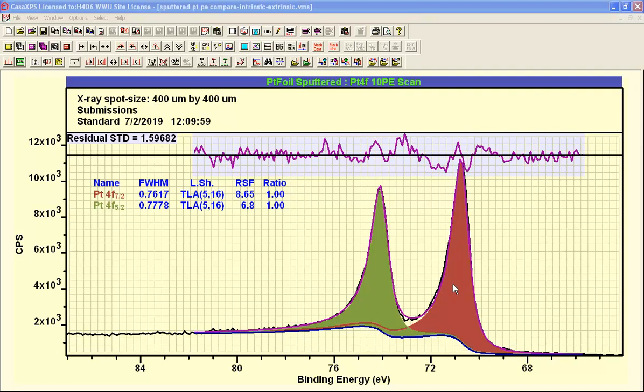In addition to the background signal, you also have the potential for loss processes to occur at the time of photoionization, but still these represent signal that arrive at the detector without undergoing scattering. In some sense, all of these represent photoemission signal in a zero loss state. We would like to model the shape of these peaks in order to work out the amount of signal we should attribute to each one of these peaks in particular.